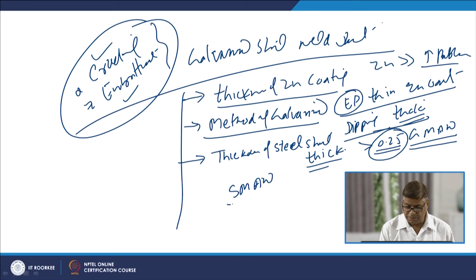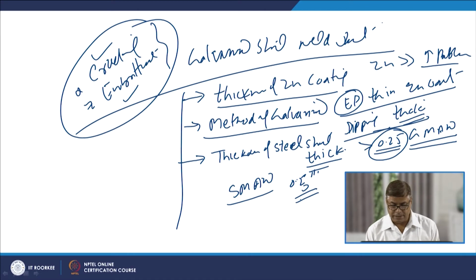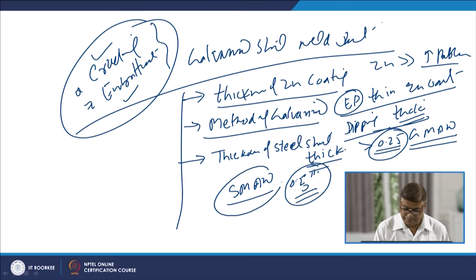like the weld joints of galvanized steels produced by the SMAW process, which do not show much cracking even up to 0.5 inch of steel sheet thickness. So, galvanized steels up to 0.5 inch thickness welded by shielded metal arc welding do not show much cracking tendency, while in case of the GMAW it shows significant cracking tendency.